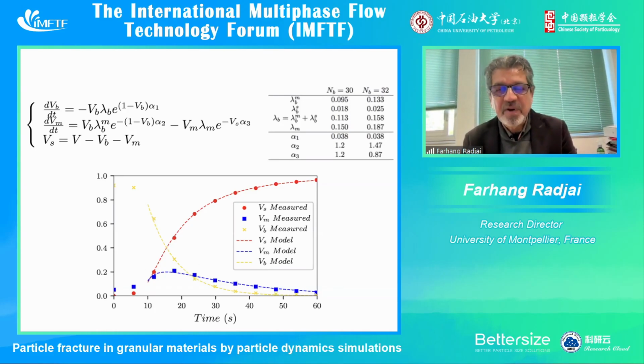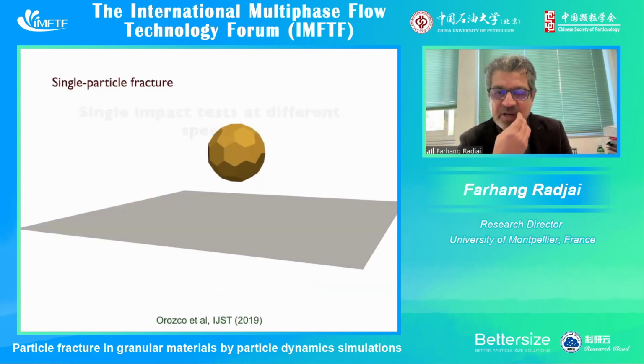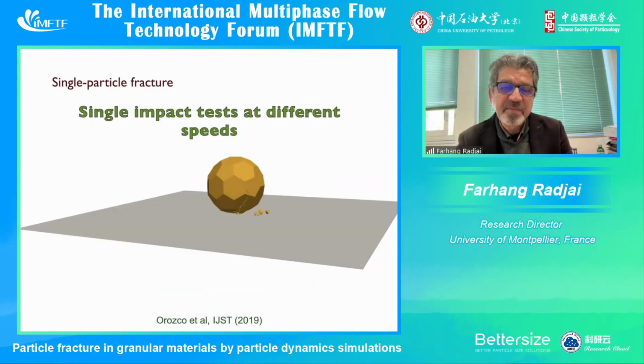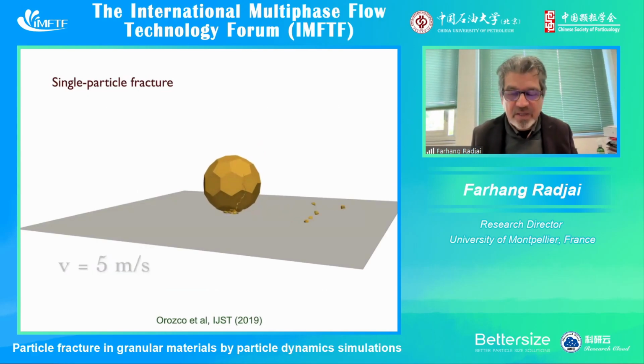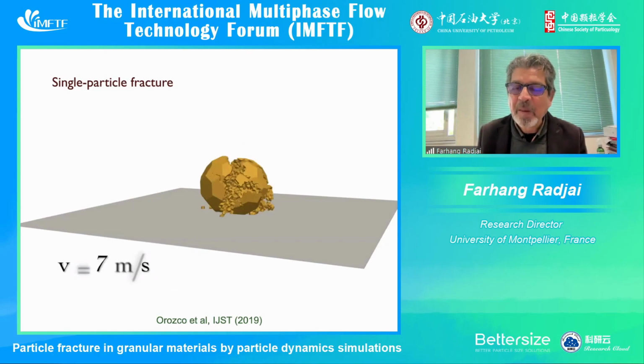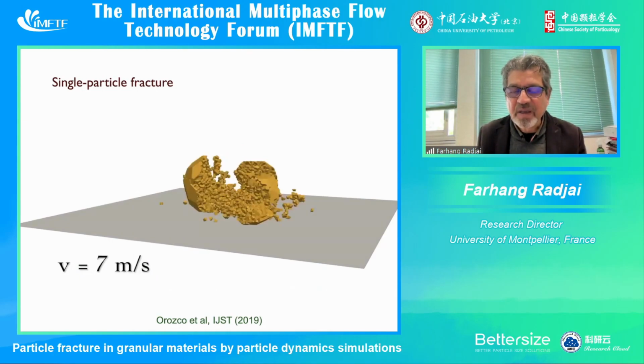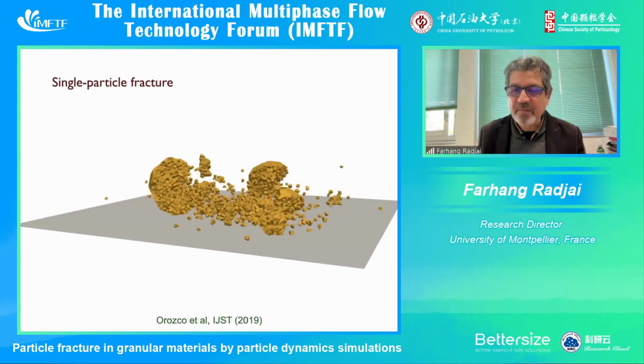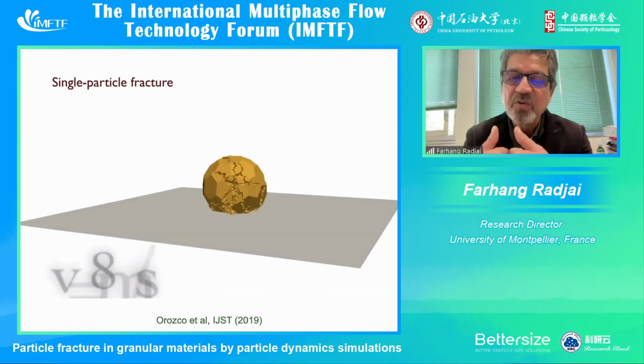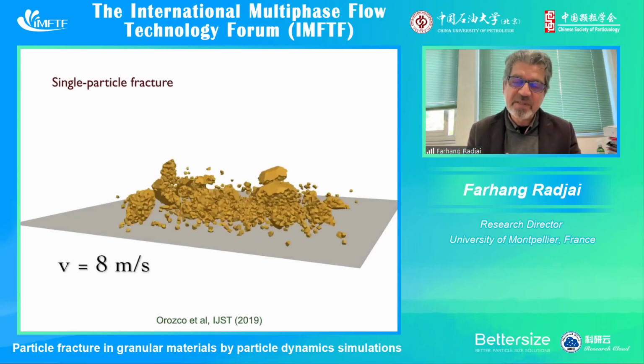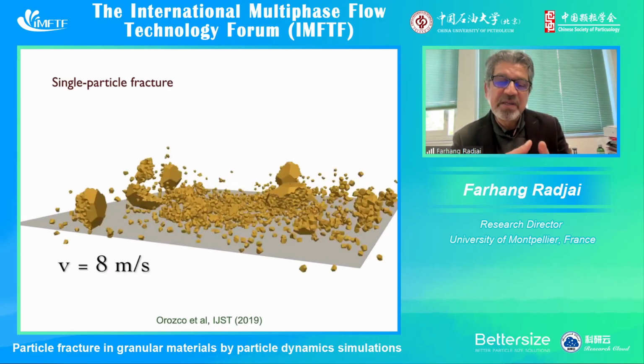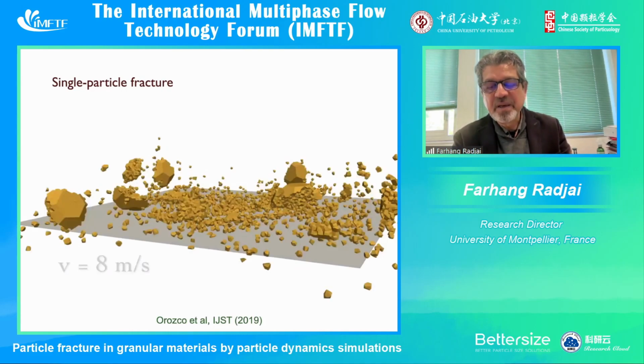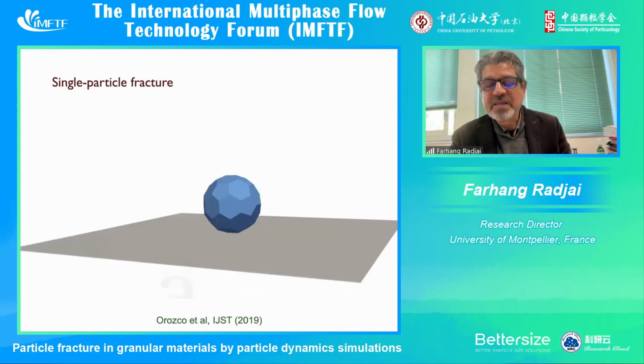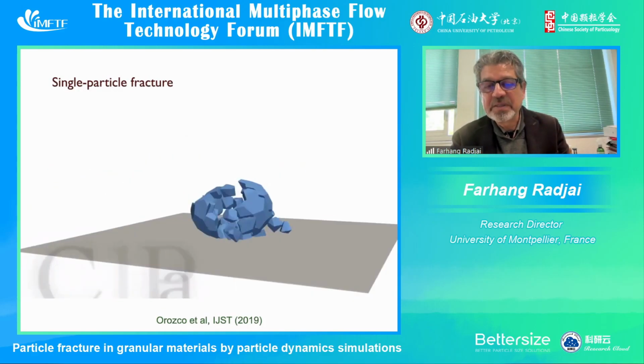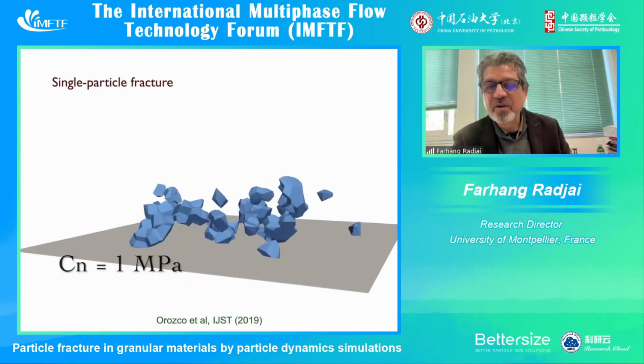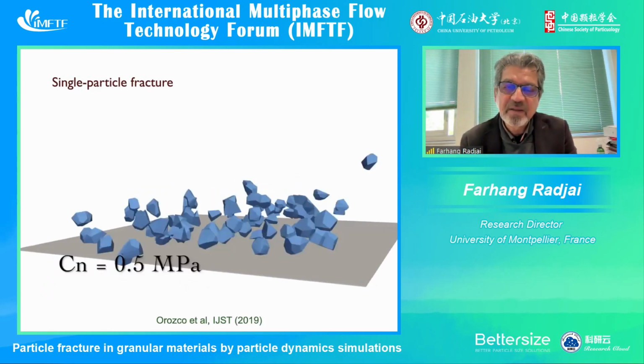For single particle fracture, we did a large number of simulations with two different methods. The first method is the contact dynamics method. In contact dynamics, which is also a particle dynamics approach, we don't use elasticity at the contact point. We don't use a spring-dashpot model for the forces, but we use an implicit approach in which the forces are calculated as Lagrange multipliers. And here, these simulations have been done using the bonded cell method together with the contact dynamics.